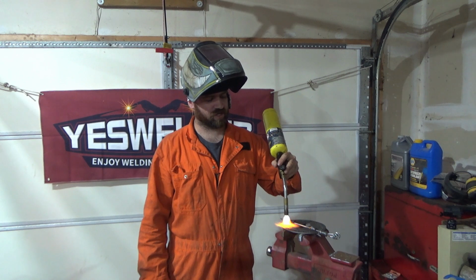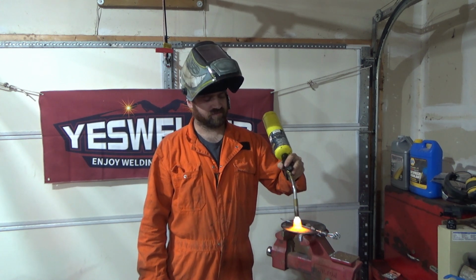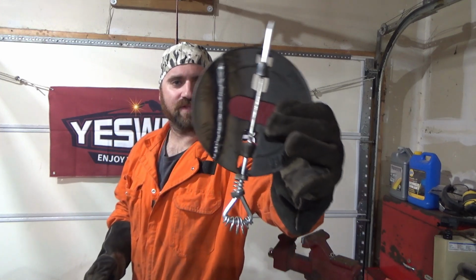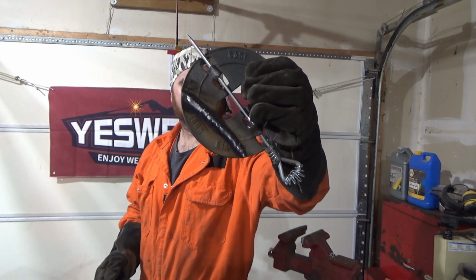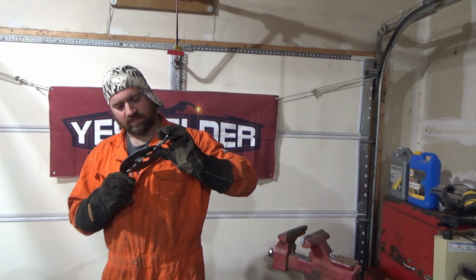To get this preheated up real good, then we're on a bead. That right there is a weld on cast iron. That went better than I thought. So these are nickel 55 rods. I got this thing up to over 500 degrees. Set my heat at about 70 amps or so. Turned my dig function all the way down to 0. And just dropped and dragged like a 7018 rod. And then after that, took a torch. Did a little bit of post heat after it cooled down a little bit to make sure that that cooling process slows way down so it doesn't cool too quick.